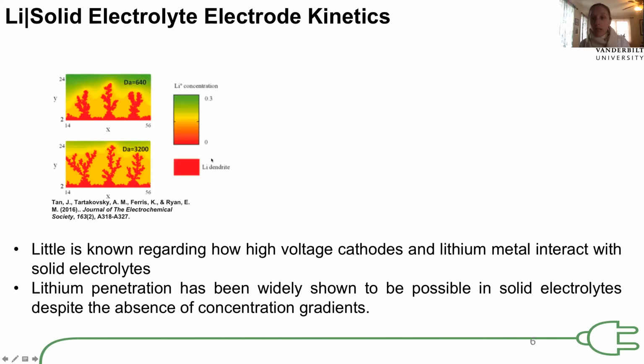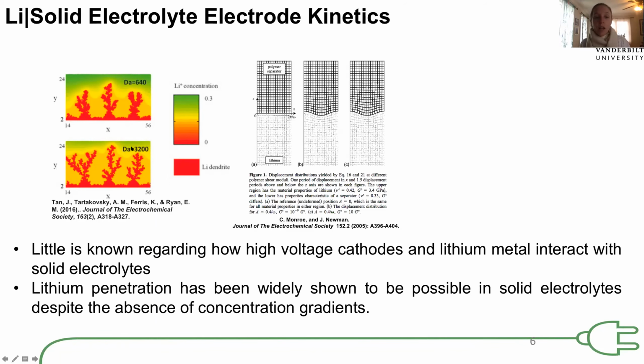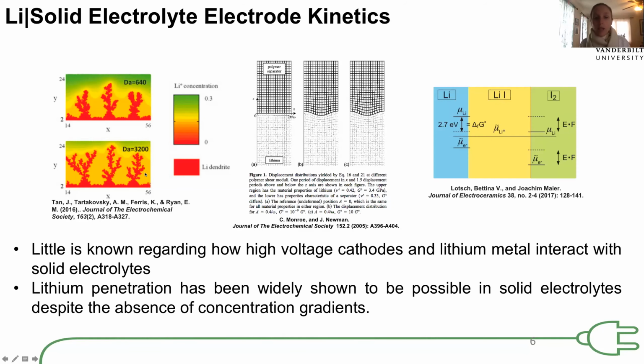And so our group has been really motivated by lithium metal and how it interacts at solid-solid interfaces. This gives you an example of these dendrites that can form in a liquid electrolyte. And this is largely governed by the formation of concentration gradients in electrolytes where the transference number is less than one. And so there's been a lot of work pioneered by Monroe and Newman, which has suggested that if I could just have a strong solid electrolyte, I could suppress this formation of a dendrite or filament, and I could reversibly deposit and dissolve lithium at a lithium metal electrode, which we have a very challenging time doing with liquid electrolytes. But in actuality, this isn't the case because the dynamics of these buried solid-solid interfaces are much more complex.